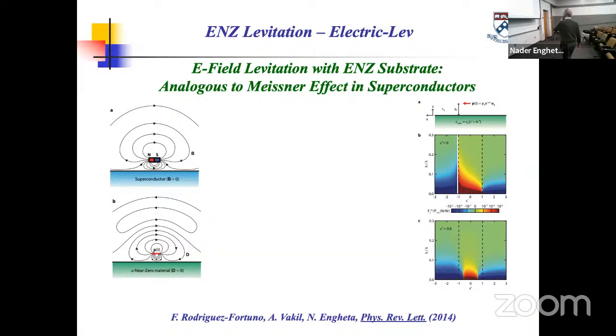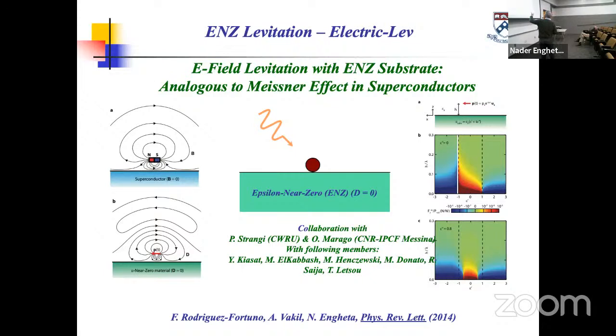Now, this theoretical result, by the way, excited two of my good friends, Pino Strangi from Case Western Reserve University and Onofrio Marago. So we put our efforts together, three groups, to see how we can experimentally verify that. This is work in progress, by the way, we are not there yet, but we have done some very interesting studies to see what happens if we have a large particle, like a micron size, on top of this. Onofrio is an expert in optical tweezing, and Pino actually built this sample layer by layer using effective permittivity, and we are currently working on that. So this is work in progress.